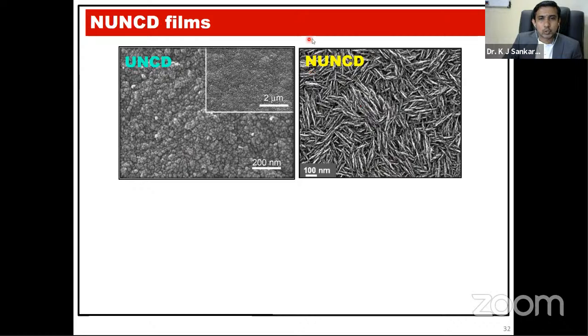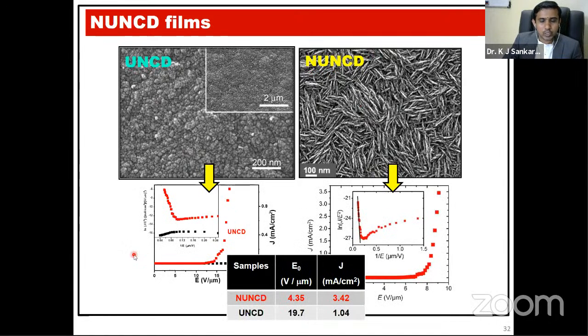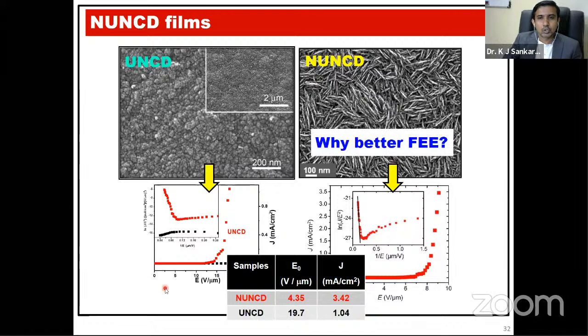So how are these NUNCDs better than the UNCD? We did the field electron emission measurements, and you can see that NUNCD has a low turn-on field and a high current density as compared to the UNCD, which has a turn-on field of around 19. So again, the question arises, why is NUNCD much better than the UNCD? So we need to know again the microstructure of the NUNCD.